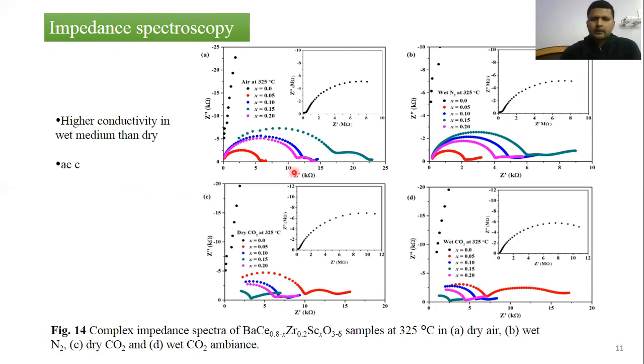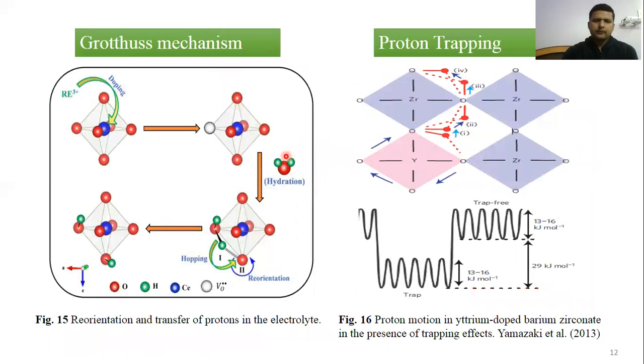We also observed that although the scandium doping leads to the creation of more oxygen vacancies, still the higher concentration of scandium shows less conductivity than the lower concentration. The reason may be proton trapping. First, let us understand how the proton transfer mechanism is going on inside the electrolyte.